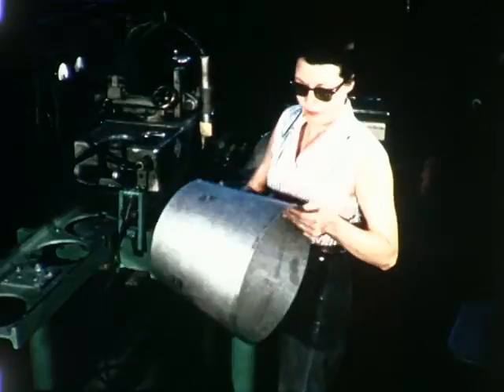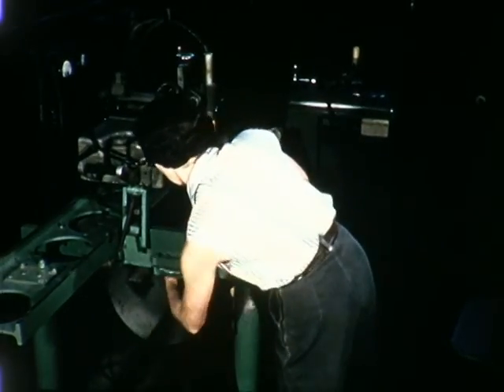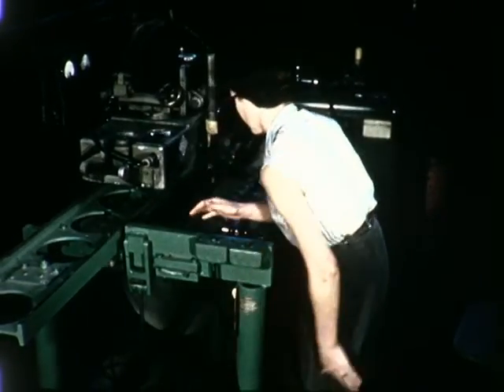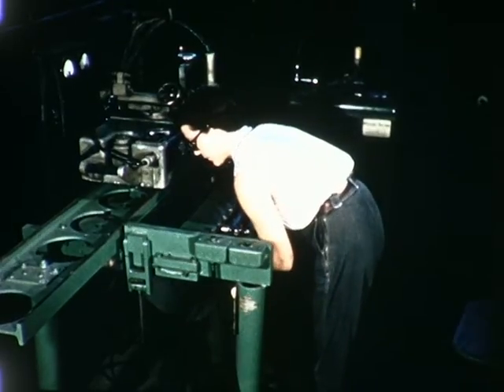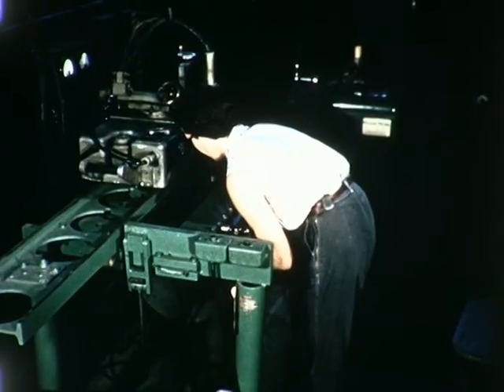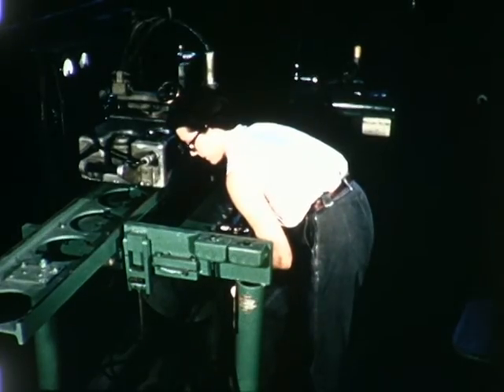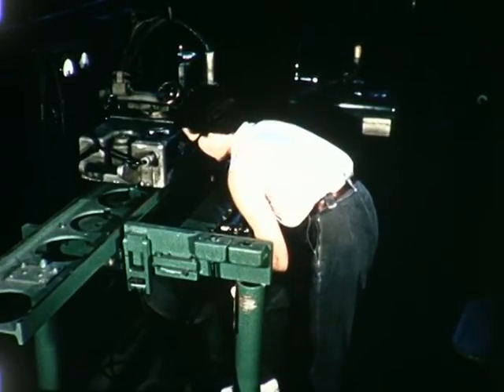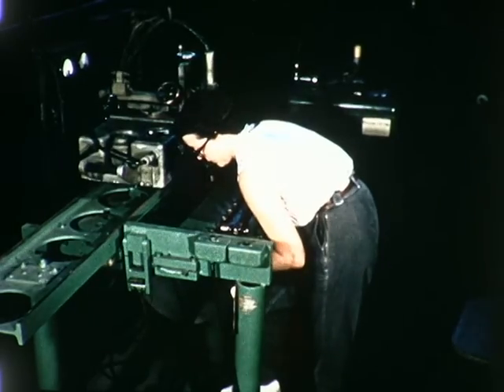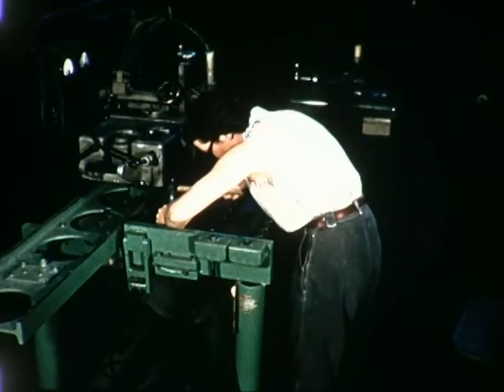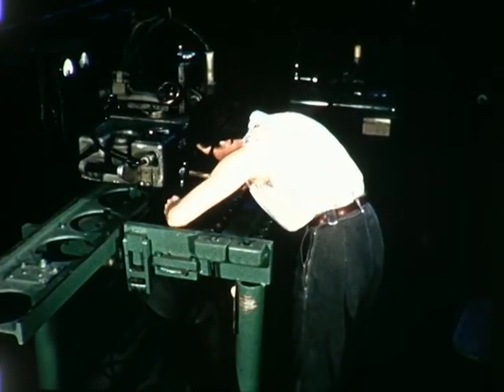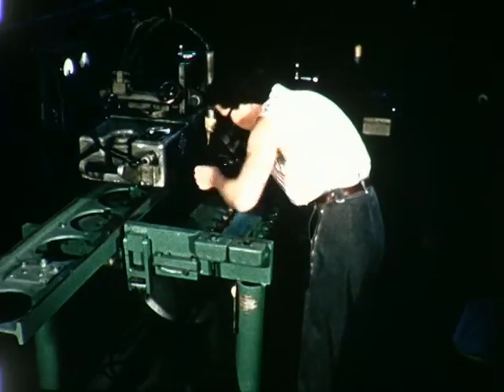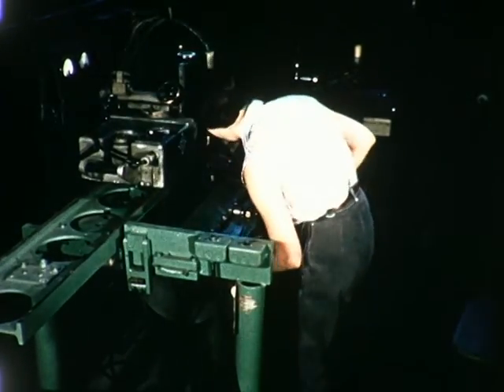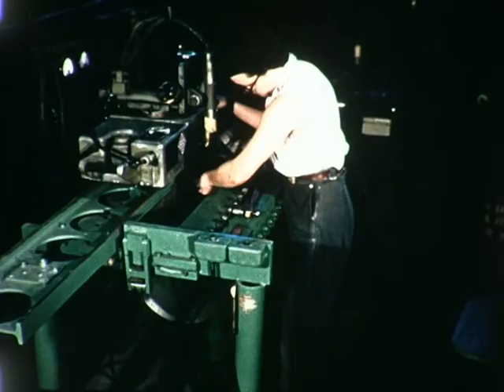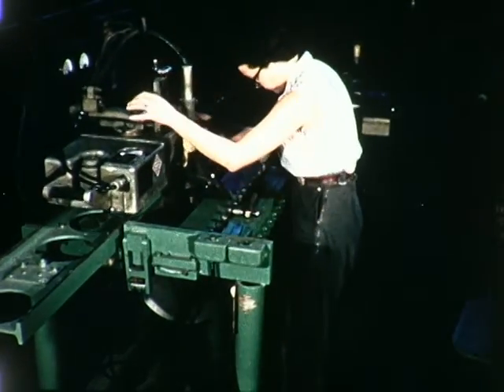Rene 41 is weldable by the inert gas arc welding process. When proper control is exercised over the influencing factors, the welds will be sound, ductile, and strong. For satisfactory welds, the following factors are considered necessary: good fit-up of parts, thorough cleaning prior to welding, and rapid cooling of the weld area to obtain maximum ductility. This may be accomplished by the use of copper backup chill bars. The use of water-cooled welding fixtures may be necessary for some applications. Parts must not be restrained during welding.